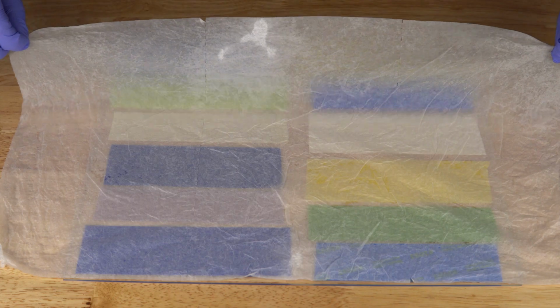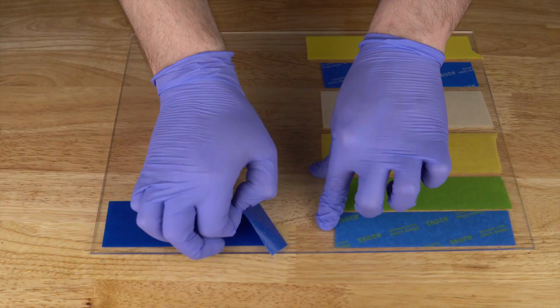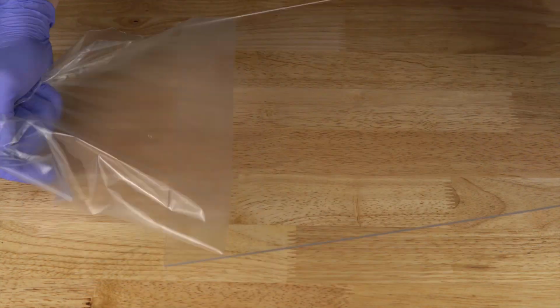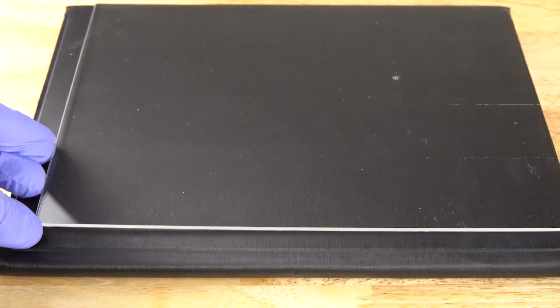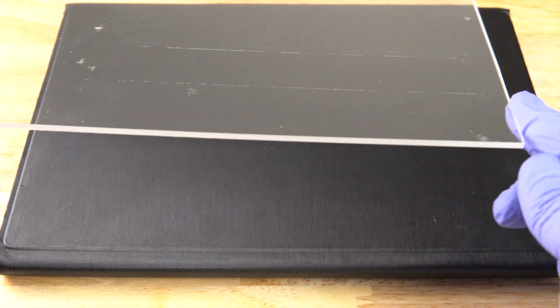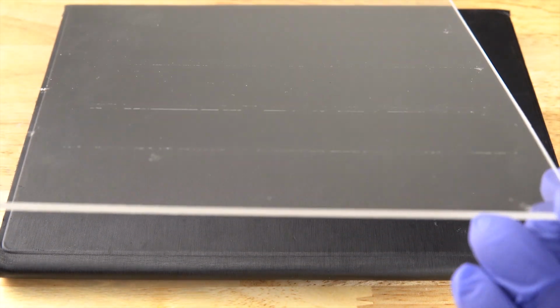Okay, it's been about an hour now, so let's remove these tapes from the plexiglass and remove the covering. As you can barely see, most tapes left very little adhesive residue with the exception of the Frog Tape. These lines are that gel that forms by hydrating that special polymer that these Frog Tape have.